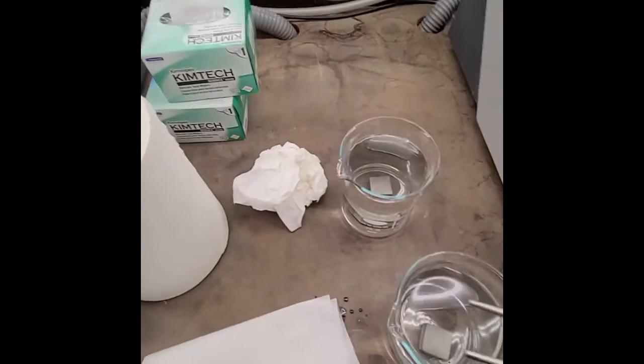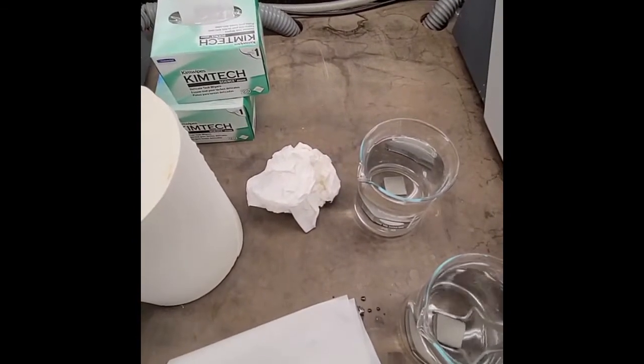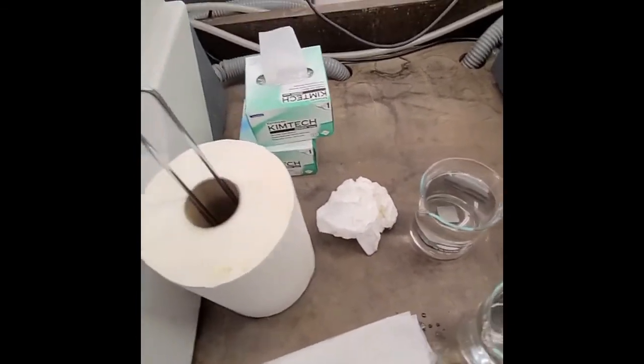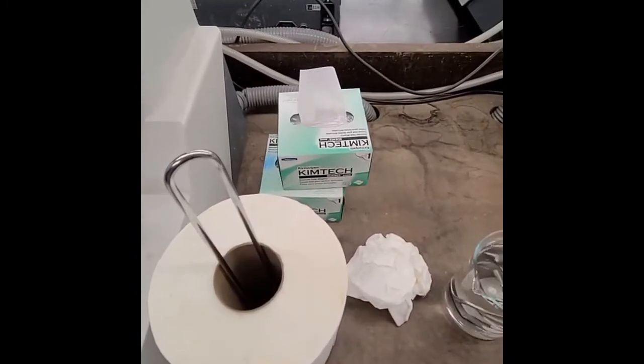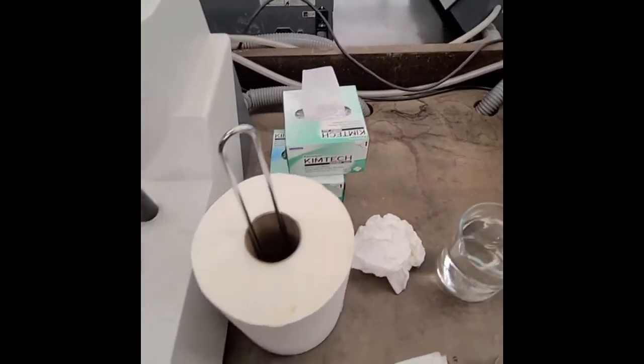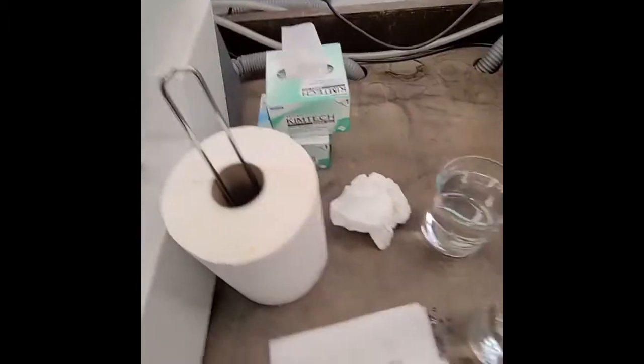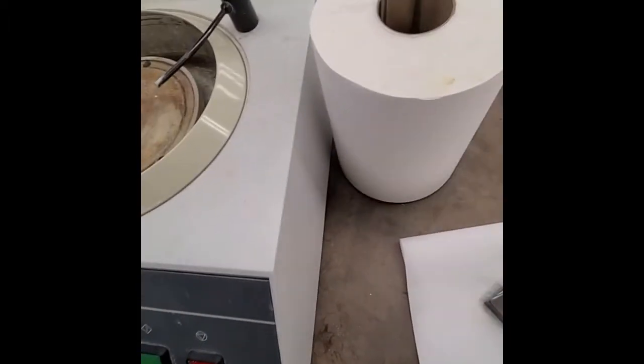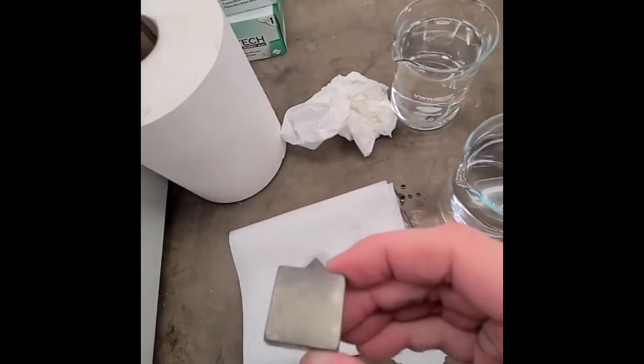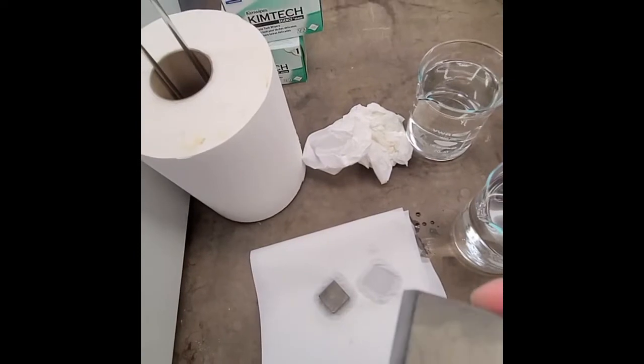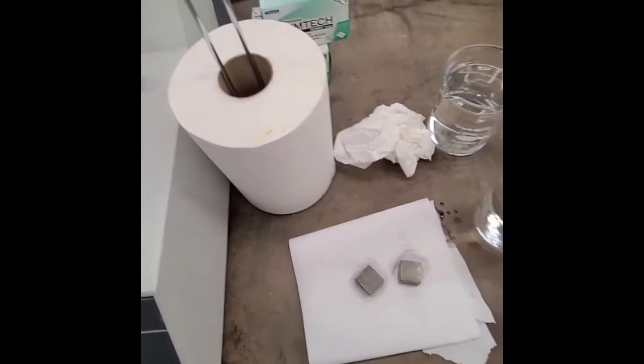All right, so those samples have just been in there for a minute or two. They cool down very, very quickly. I'm gonna take them out, dry them off. One thing we'll notice is that the surface of the sample is a slightly different color than it was before. So it's a little bit more matte. And that's just because it's been in there. This furnace is not a vacuum furnace or anything like that, so it has a little bit of oxide on that surface.